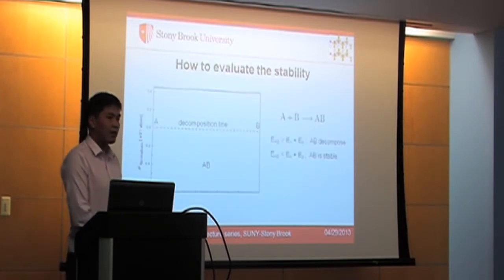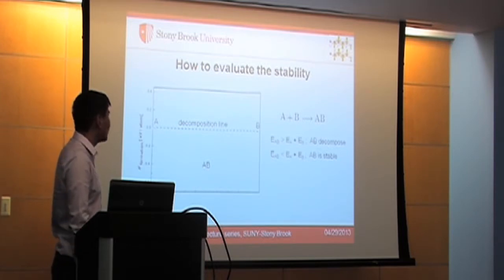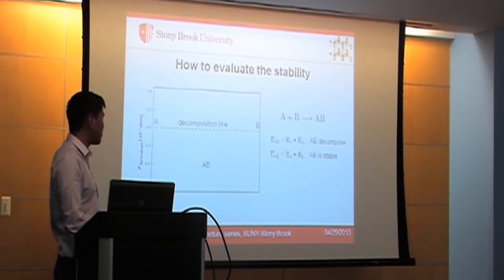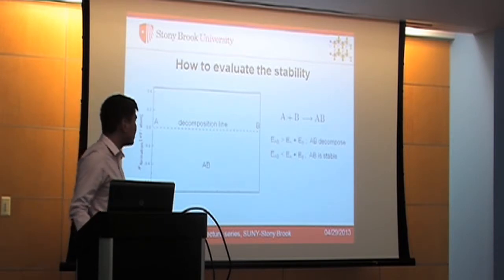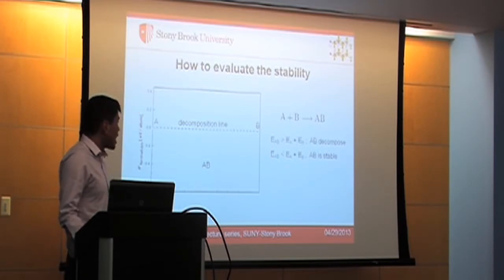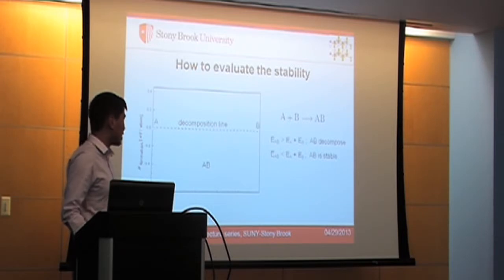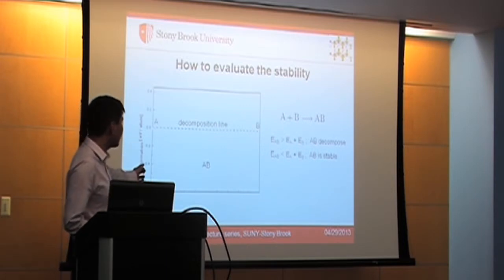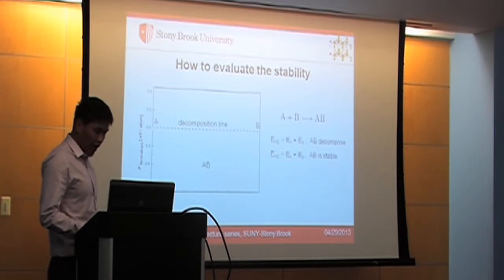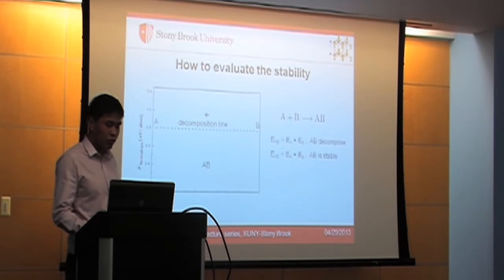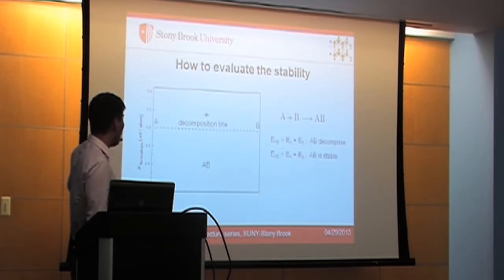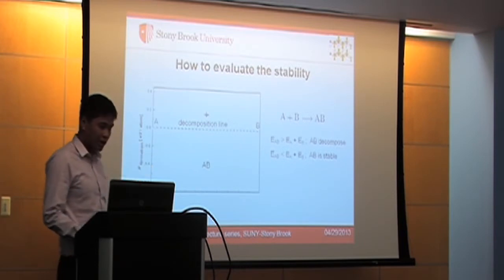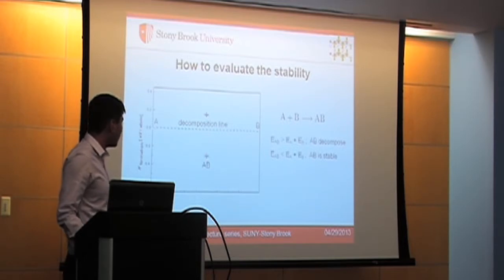Before we analyze our results, I'd like to give a very brief introduction about how to evaluate the stabilities for the compounds with different chemical compositions. Suppose we have two elements, A and B, and if it forms compound AB, if the formation energy of AB is negative, then we say compound AB is stable. Otherwise, it's unstable. We can transform this reaction into the left panel of the graph, so that if we have a structure which has energy above the so-called AB decomposition line, then we say this structure is unstable. If the energy is below the line, then it's stable.